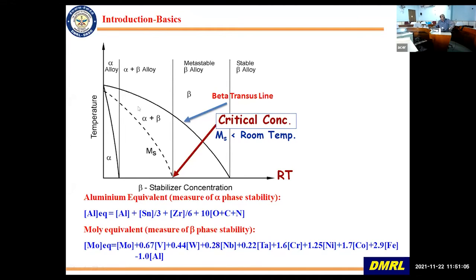So above this temperature line is what you get is beta phase, which I will show you the crystal structure. Now, this is a very important temperature as far as titanium alloy goes, and this is called the beta transus line. And in titanium alloys also, you can see this dotted line, which is the martensite start line. So in titanium alloys also, you have martensite formation, but it is not as strengthening as in steels.